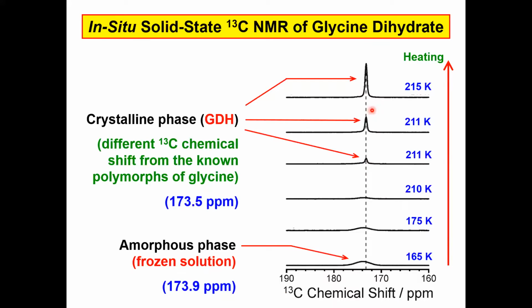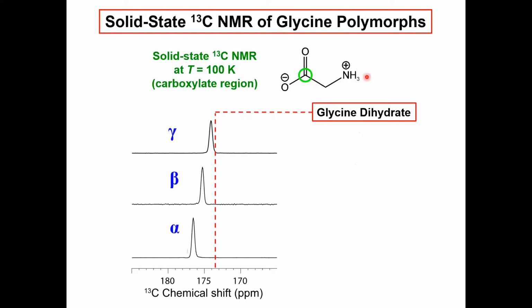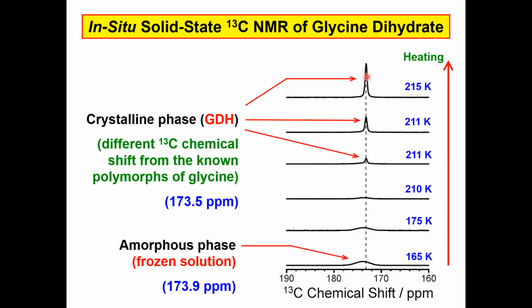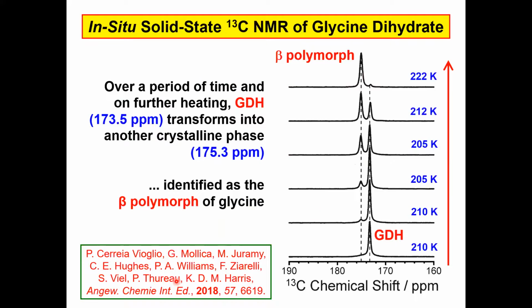Now, the important point is this signal here is different from any of the polymorphs of pure glycine, and indeed using a range of other experiments, which are described in this paper, but I'm not going into detail here, we could show using HETCOR and other methods that the signal from the glycine dihydrate is fully compatible with the published crystal structure. And if we leave the glycine dihydrate for a longer time and also heat it, a transformation occurs to the beta polymorph of anhydrous glycine as shown there.